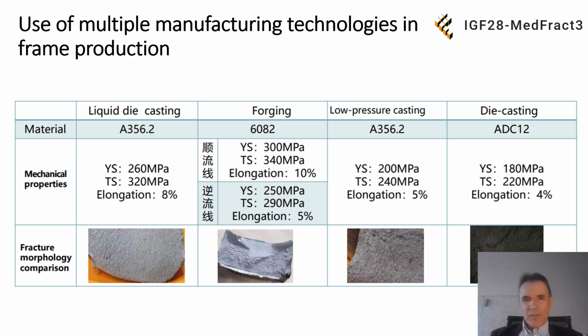Technological processes. From this table it is possible to see the different tensile properties caused by different technological processes in the production of these bicycle frames. For example, liquid die casting is one process, forging is a different technological process, low pressure casting, die casting or hydroforming. These are typical processes for producing parts from aluminum alloys, and all these procedures lead to different tensile properties, such as yield stress and ultimate stress, and it's clear that this also leads to rather different fatigue properties of this material due to these technological processes.